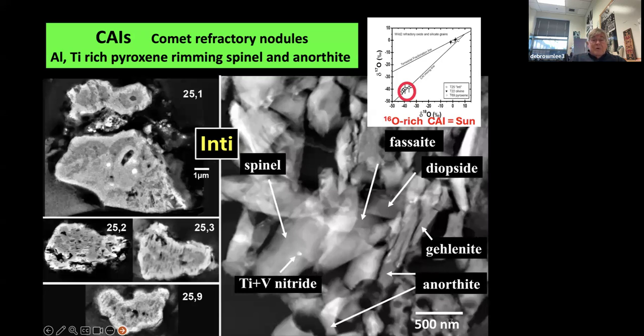One of the most exciting things we found early on was calcium aluminum inclusions. The first one we found was INTI, a very large particle, about 25 microns, made out of a collection of nodules that are just micron size. It had an isotope composition the same as the sun. So it was really exciting.